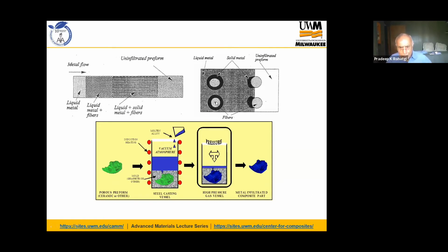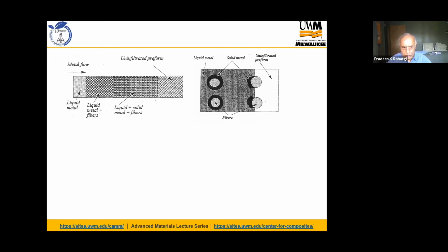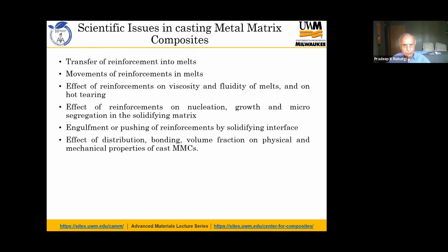And this has now been upscaled where you do 3D printing of a ceramic preform, incorporate that preform in a mold, melt liquid metal on top of the mold, and apply pressure so the liquid metal infiltrates the ceramic preform to produce a near net shaped casting of a metal matrix composite. So these kinds of industrial processes are now available.